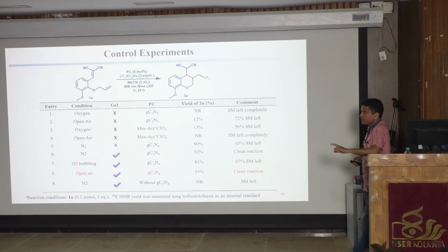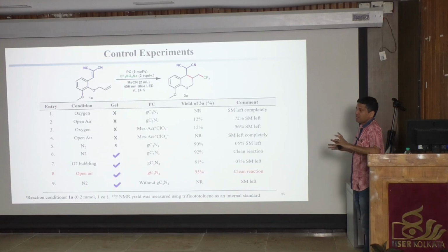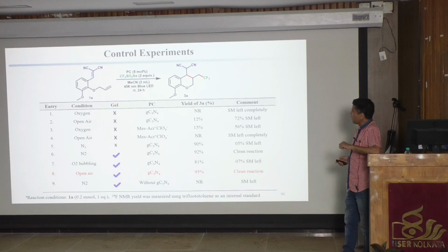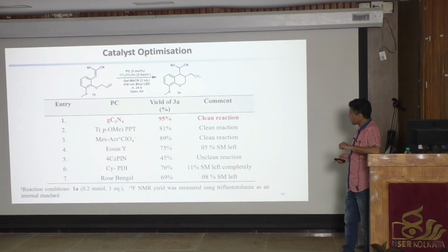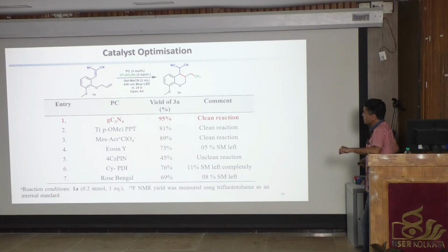If we compare the previous one and this one, in the previous one, a 2D molecule was converted to a 3D molecule, and due to this size exclusion, it ruptured the gel fiber, and the gel turned to solution state, and then oxygen intervened and stopped the reaction. But here, there is no such three-dimensional molecule, so the gel fiber is intact, and so we are getting the reaction with 95% conversion.